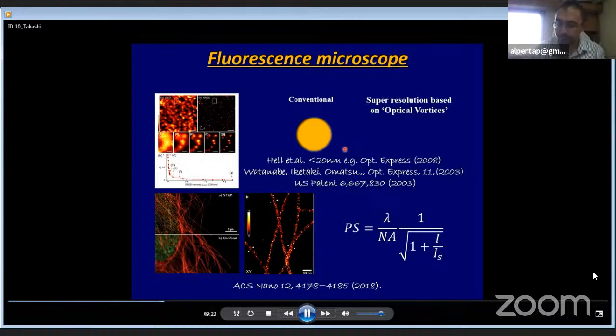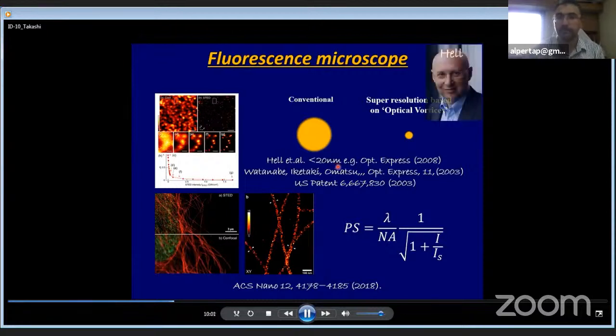Okay? In order to break the diffraction limit of the light, we overlay an optical vortex on the pump region to suppress the fluorescent signal from the target through stimulated emission or high excitation. So we can expect the fluorescent signal to come just from the central dark hole of the optical vortex. We can significantly improve the spatial resolution of the fluorescent signal up to the 20 nanometer scale. This technology was proposed by Professor Stefan Hell at the Max Planck Institute. They achieved beautiful nanoscale optical microscope images in biomedical cells. He received the Nobel Prize in 2014 in chemistry.